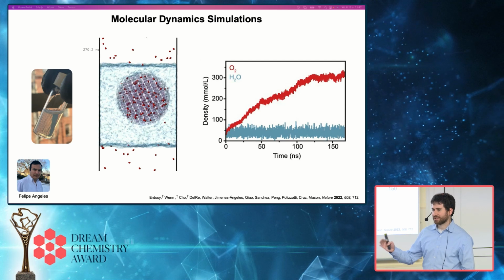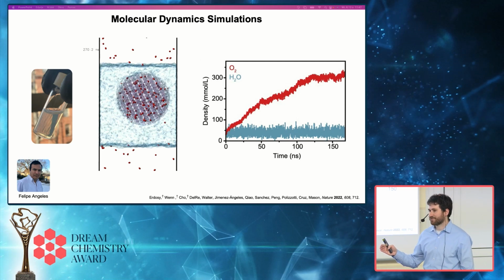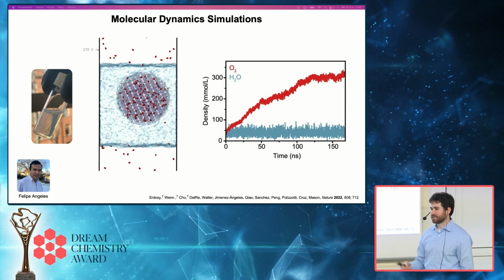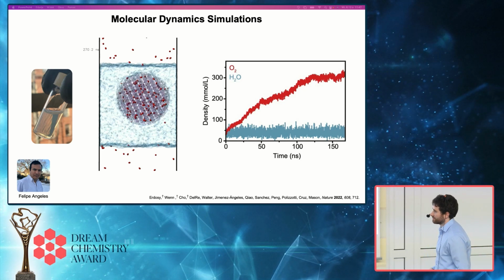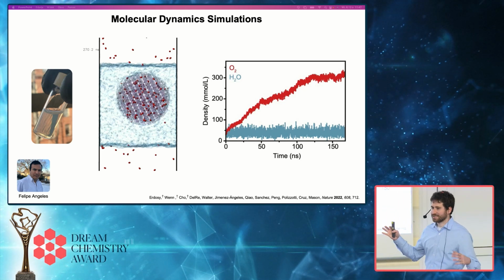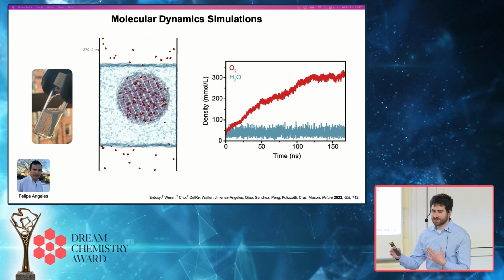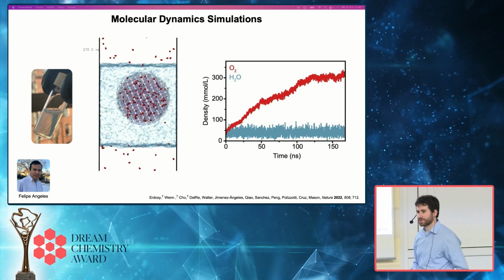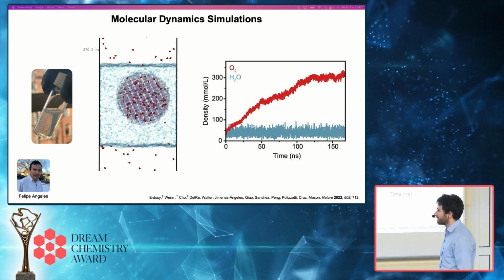Gas exchange with the surrounding environment we predicted would be very fast because gas uptake is so weak within these materials. So it's really this high internal surface area that's leading to this enhancement in gas density. It's not strong interactions with gas, like with oxygen in hemoglobin.